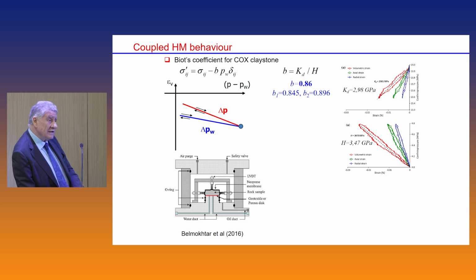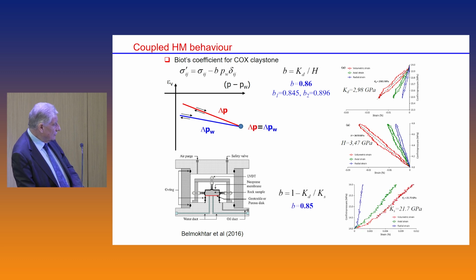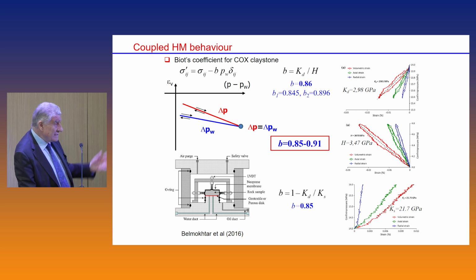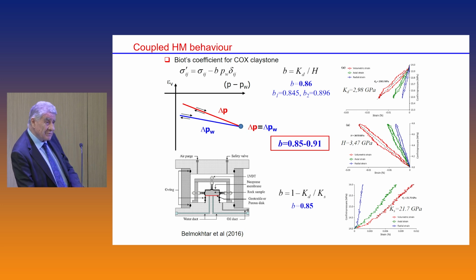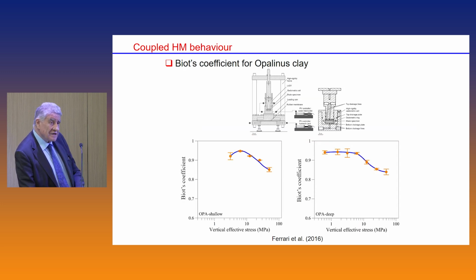But you can do it independently, and they did, using unjacketed tests that allow you to compute the volumetric stiffness of the solid phase, and they obtained a very similar result, which actually gives confidence that this is probably quite right. They did more tests and they ended up in this range between 0.85 and 0.91. Also, more or less at the same time, Opalinus clays were being tested in a similar way, and they ended up with values around 0.9.